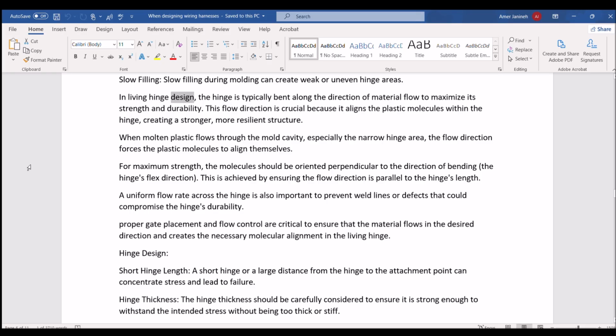In living hinge design, the hinge is typically bent along the direction of material flow to maximize its strength and durability. This flow direction is crucial because it aligns the plastic molecules within the hinge, creating a stronger, more resilient structure. When molten plastic flows through the mold cavity, especially the narrow hinge area, the flow direction forces the plastic molecules to align themselves. For maximum strength, the molecules should be oriented perpendicular to the direction of bending, the hinge's flex direction. This is achieved by ensuring the flow direction is parallel to the hinge's length.